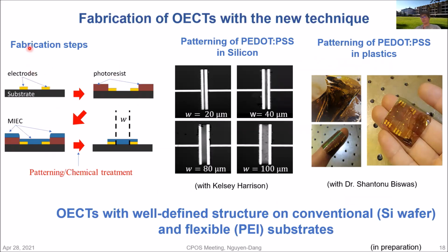Following the fabrication steps shown on the previous slide, I could pattern PEDOT:PSS on silicon in a very precise way. I present this work in one slide, but it doesn't take into account hours of optimization, and I would like to thank Kelsey for helping me with that. In this picture, you can see the channel right here in between the two electrodes, and the channel width is increased from 20 microns to 40 microns, 80 microns, and 100 microns. And it can be very neat.